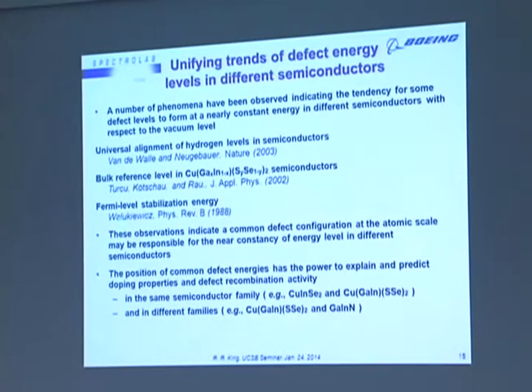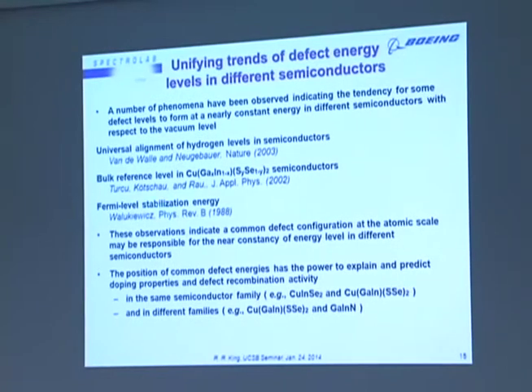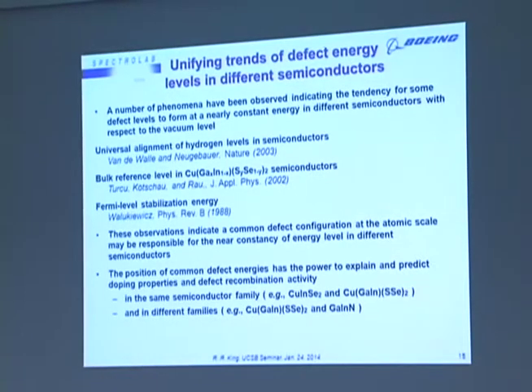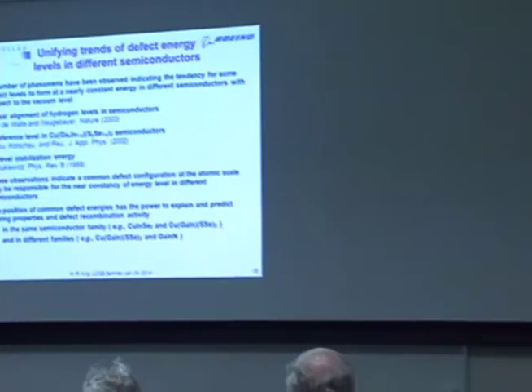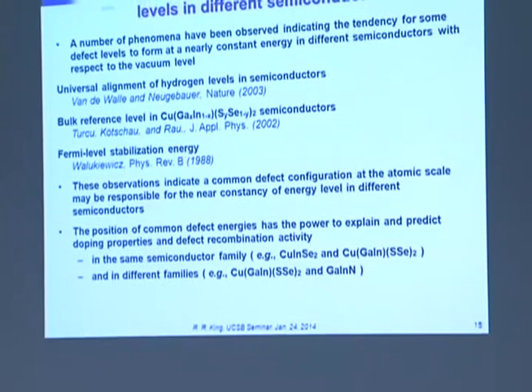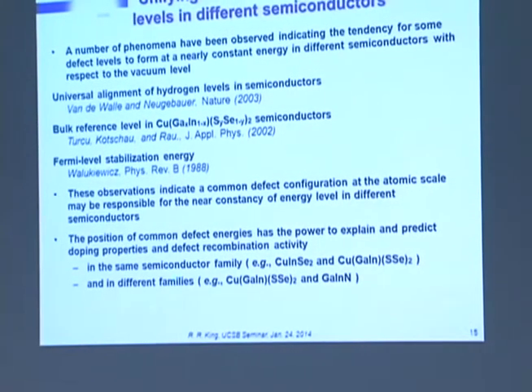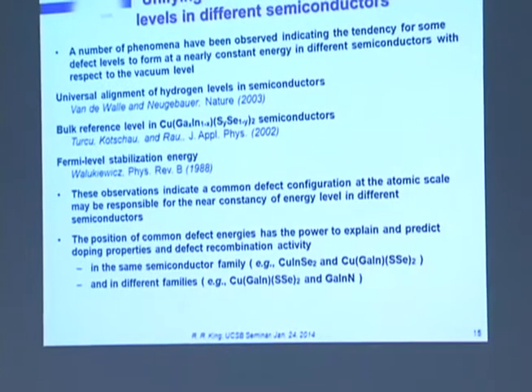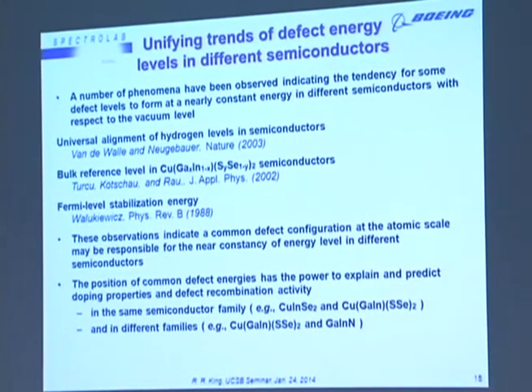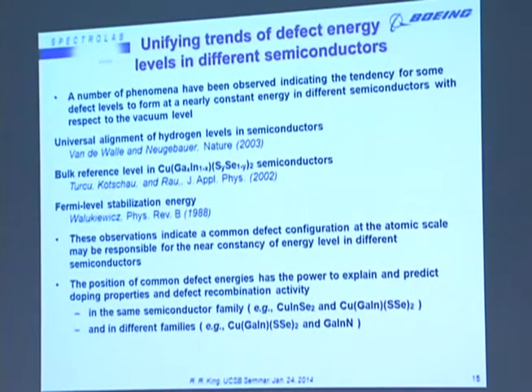And Walukiewicz has done some interesting observations of the Fermi level stabilization energy, which we'll talk about a little bit more, in which defects formed by damage to the lattice also tend to appear at the same distance from the vacuum energy level. So these observations indicate that there are some common defect configurations that result in a near constancy of energy level. And these trends, which are universal among semiconductor families, have some power to explain and predict the doping properties of defects in the same semiconductor family.